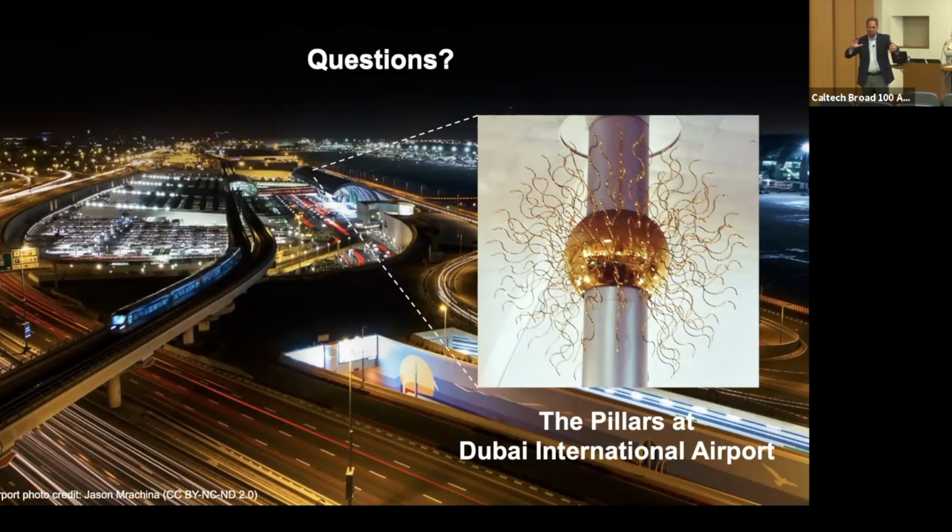So if I take a lattice, for example, that's been made, and I apply pressure, it'll compress, right? That gives you a feel for the compressibility. And I can tell that because the optical properties of the lattice will change as the particles get closer together, in the case, for example, of gold cores. And then if I relax, it'll rebound back to the original state. So very flexible.